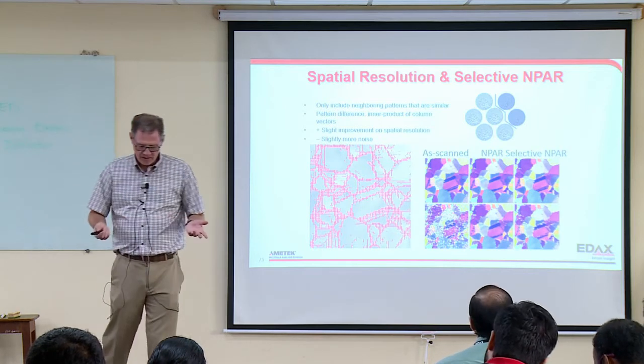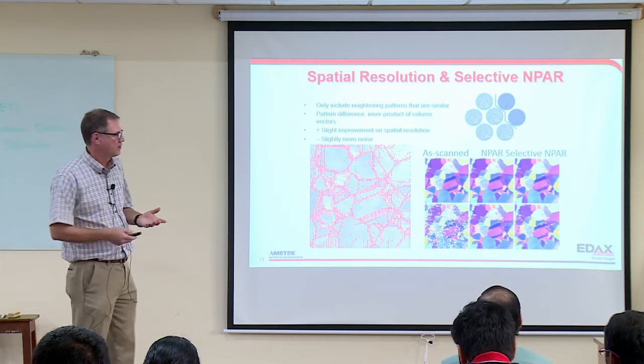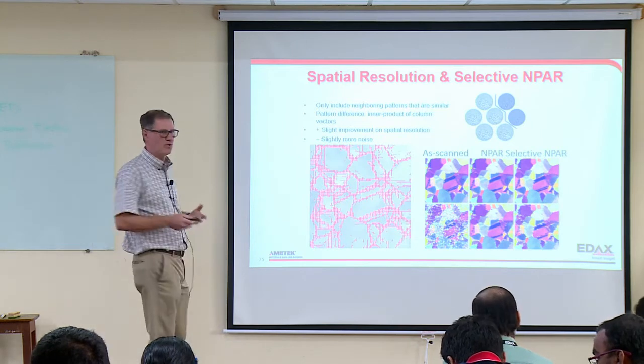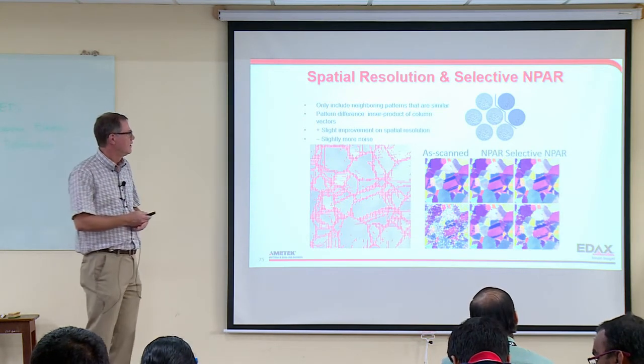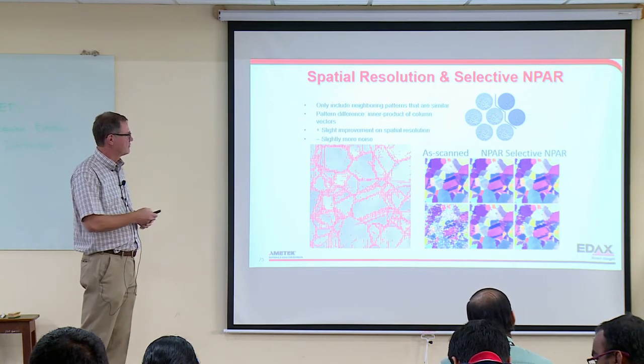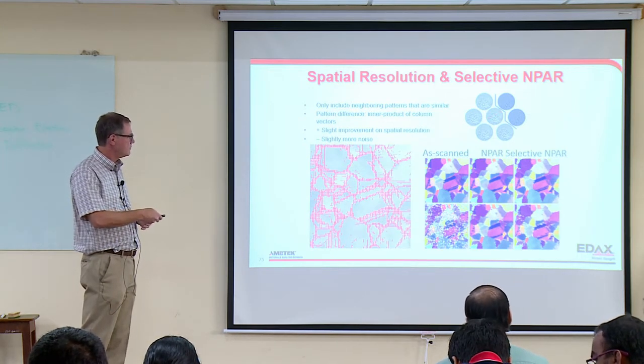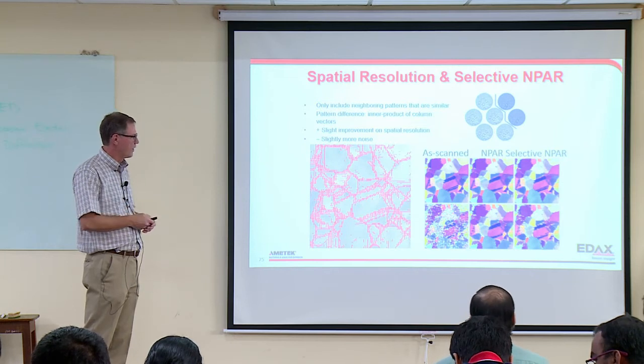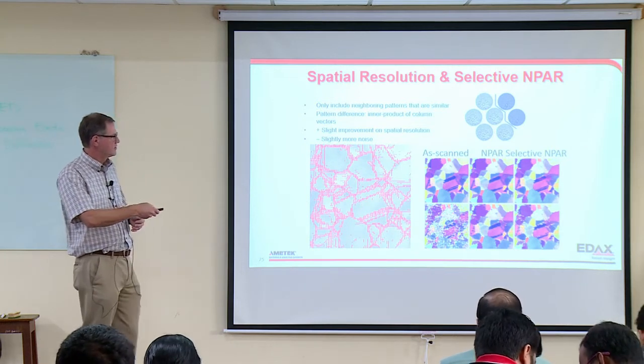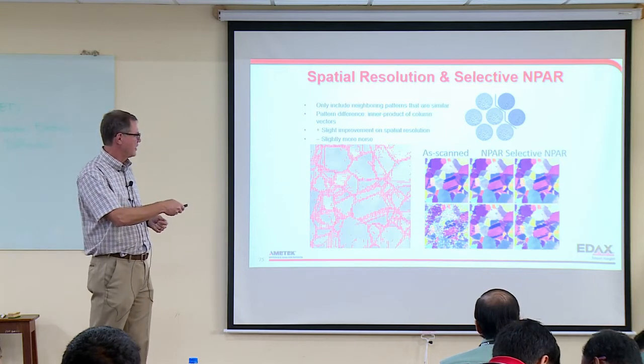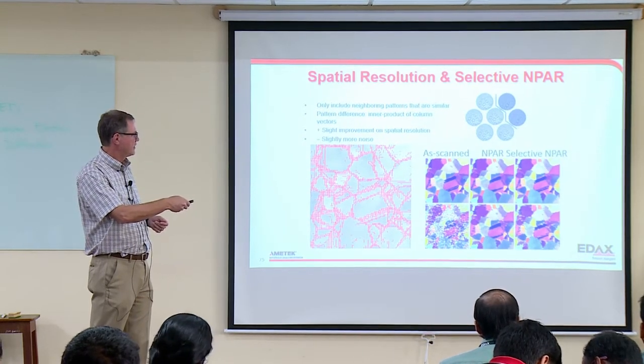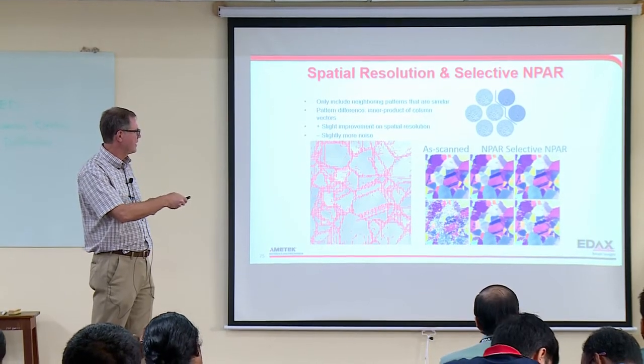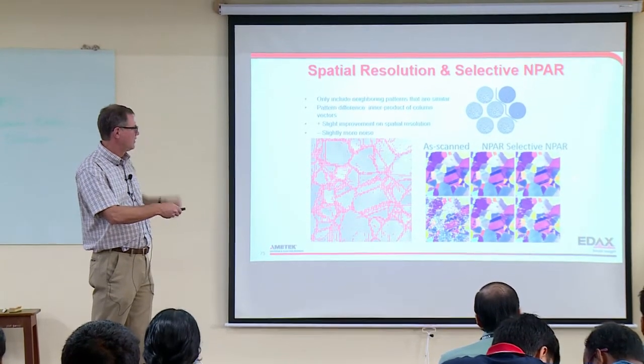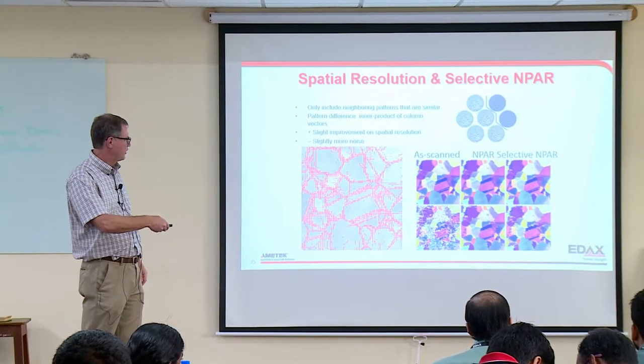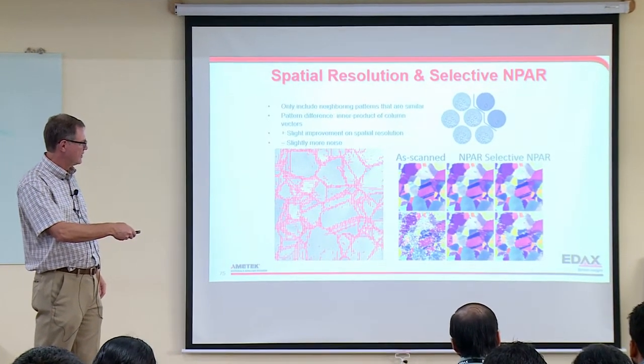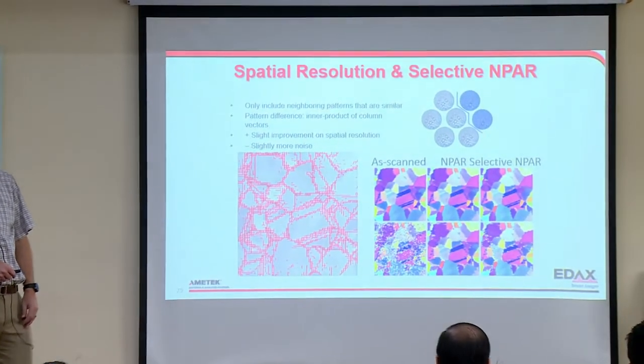So we came up with an idea of doing some pre-filtering. Can we check the patterns and see if they're the same before we put them into our averaging routine? And so the idea was only to use patterns of similar type. We have to come up with some way of doing this. So this is as scanned, this is the NPAR, it smeared it. If we use this selective technique where we throw out patterns that aren't the same in our little averaging kernel, then we do pretty well. But this is on good data. If we go to poor data, you see hints of that second twin, but it really didn't do the job.